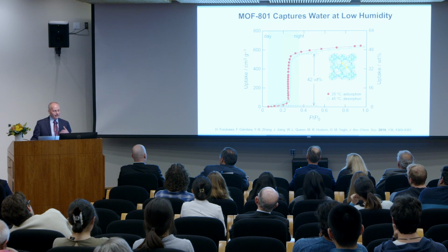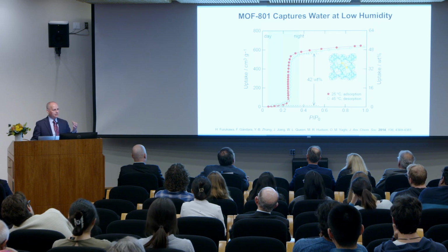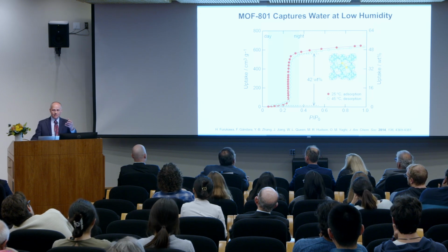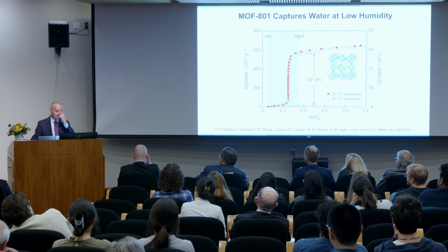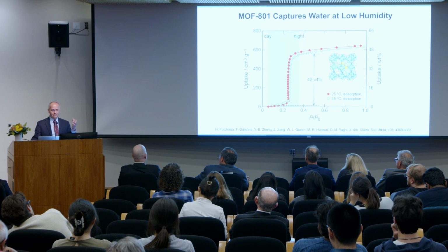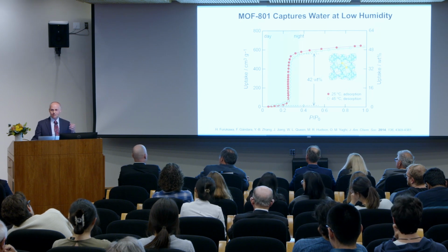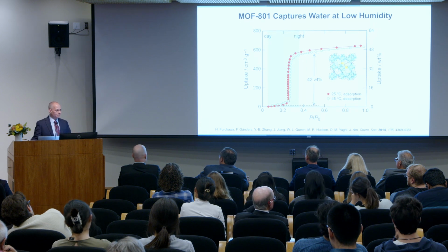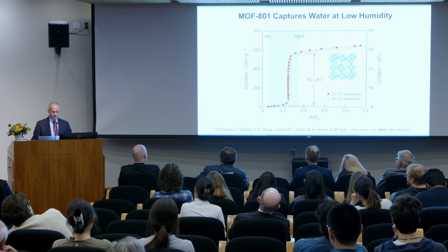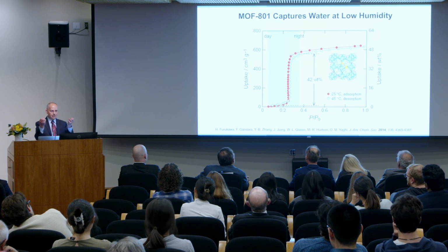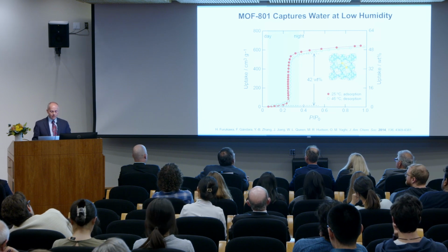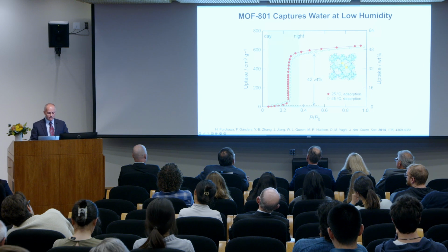So normally, in materials that take up water, like the desiccants you might have in food products, zeolites, chemists know about zeolites, they take up water from low humidity, but you have to heat them up to 300 degrees Celsius to get the water out. In fact, as a student, we used to heat those overnight to get all the water out. Well, that's not economical. But here, because of the organic and the inorganic components, you can take the water out at low humidity, at low temperature.